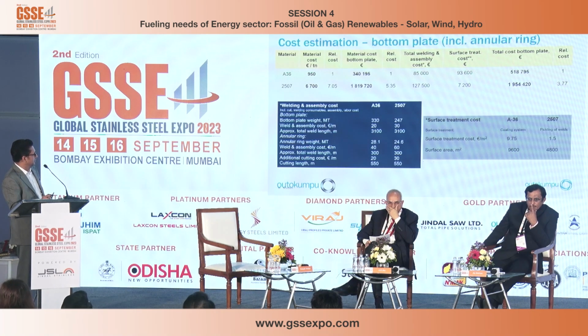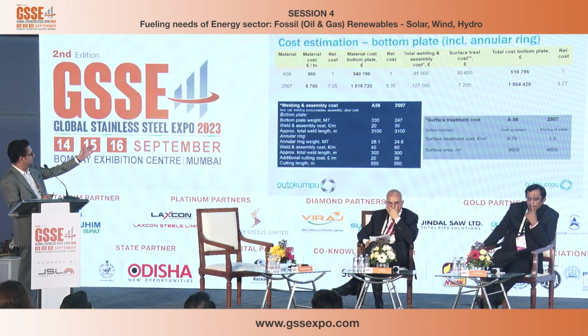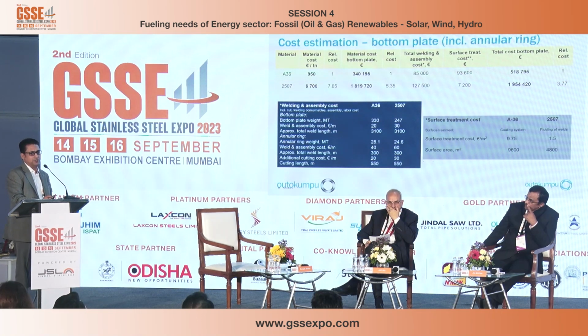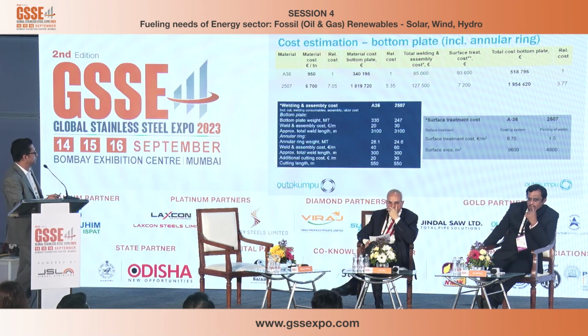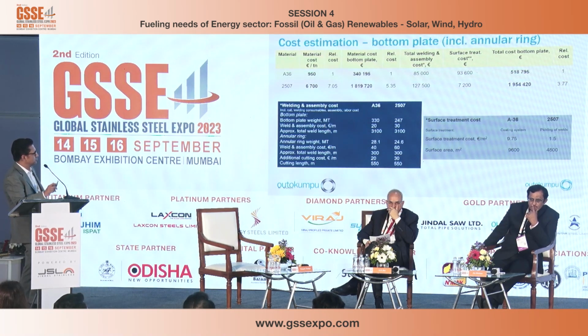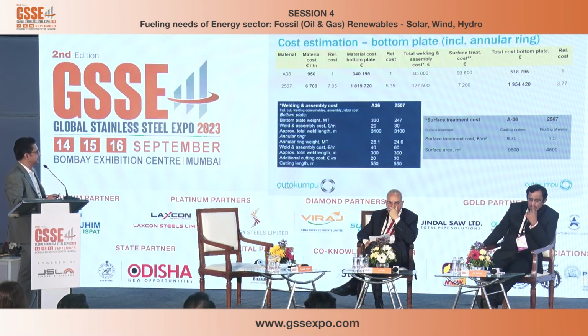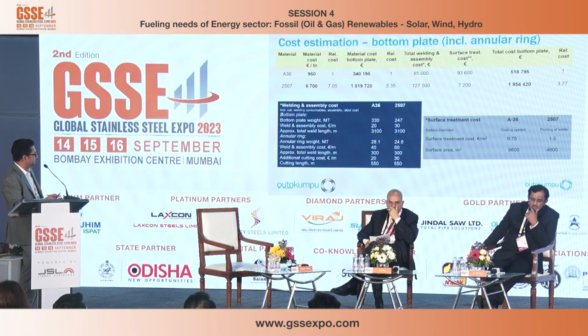Now what you have to do, I have multiplied 950 by the weight of the material that we calculated in the last slide for bottom plate plus annular ring. So you get a cost for the initial material of 340,000 euros. And for the Super Duplex, it is 1,819,720. Since we have reduced the weight, you can see that the relative difference of 7.05 times has reduced to 5.35 times. Still, it is very high.